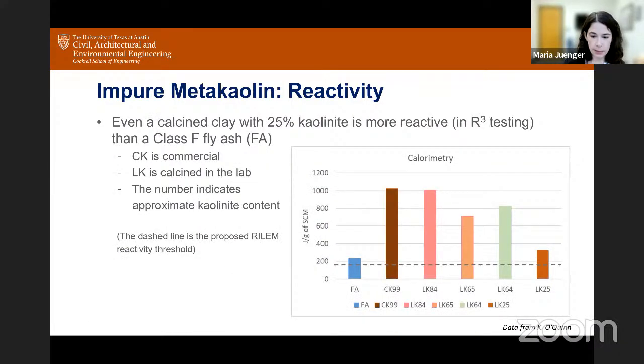I have other examples here from another research study. This is from my current student, Caitlin O'Quinn, where she's looking at a lot of different impure metakaolin sources. The ones that say C are commercially produced materials. So this is CK99, a commercially produced 99% pure metakaolin material, whereas the L ones are ones that are calcined in the laboratory. So LK25 only has about 25% metakaolin in the system.